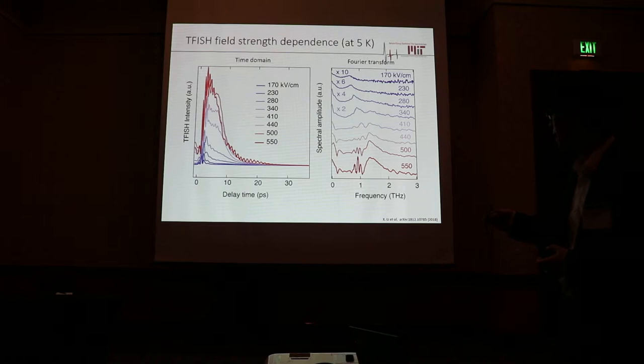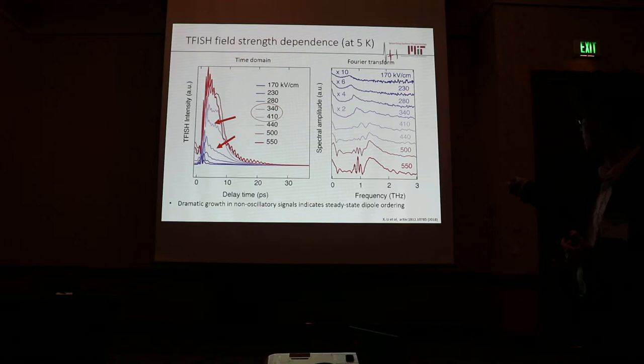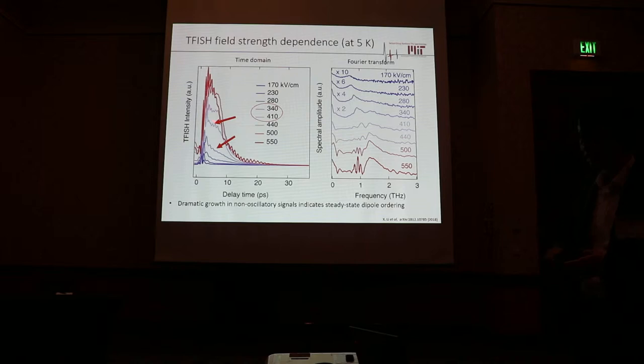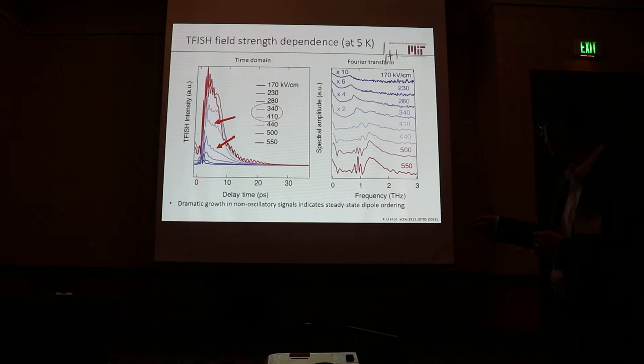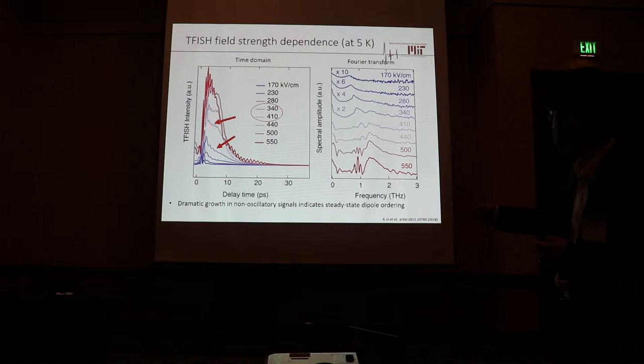If you also look at the time-domain response, a small increase in the terahertz field strength results in a doubling of the non-oscillatory signal component, which indicates the rise of a steady-state dipole ordering. As we increase the field strength, the non-oscillatory signal stays longer and becomes flatter, indicating that the ions actually stay at the off-center position for quite a while before they relax back. This is a metastable ferroelectric state.